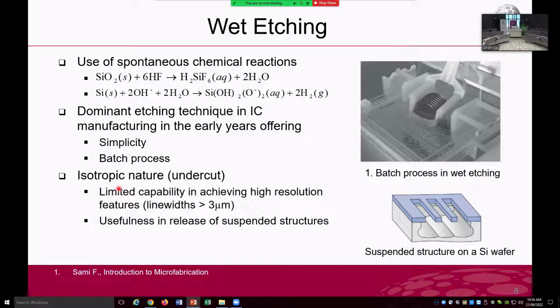That's one critical limitation. Another limitation is the highest aspect ratio. The highest aspect ratio you can achieve from wet etching is 1 to 2. That means when you etch a trench structure, if the width of the trench is 2 micron, then the maximum depth of the trench is 1 micron. You can't go higher than that. That's the maximum aspect ratio you can achieve from this isotropic process.